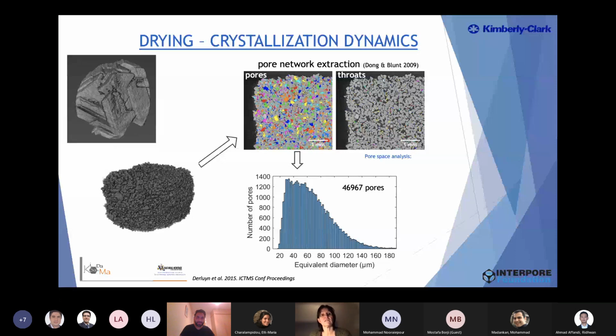If it was originally filled with a salt solution with a certain gray value, then two things can happen when you dry it out: it can dry out and become filled with air, and the gray value becomes darker for air, or the salt crystallizes out in this pore.